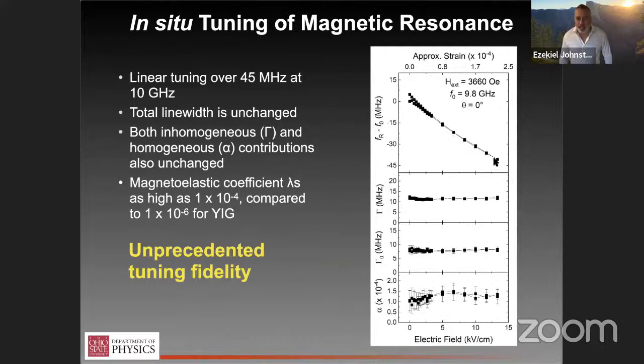here there's a more systematic study where we show that this tuning is reproducible over 45 megahertz, and the damping or the loss by any measure, whether it's total line width, inhomogeneous broadening, or homogeneous broadening, we see no change over this strain. So this is a very reproducible and benign perturbation of the system, but it allows us to tune in situ the magnetic resonance. And I really want to point out that this is yet another remarkable feature of this material system, that there's a 2 order of magnitude larger magnetoelastic coefficient lambda sub s than YIG.